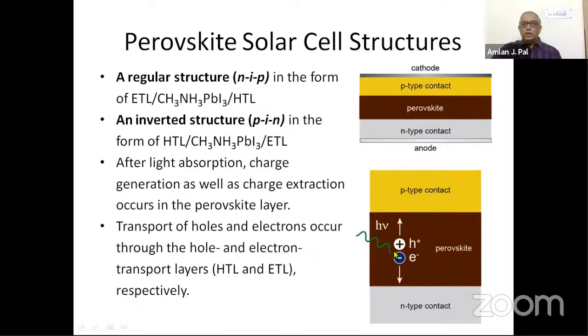So as soon as light falls, you have some kind of electron-hole formation in the perovskite. And because of the band diagram, as I said, we have chosen the P-type material and the N-type material in such a way that they form some kind of type 2 band alignment at both the interfaces, and because of this type 2 band alignment, charge separation will occur, and the holes will move towards one electrode and electrons will move to the other electrode and give you current in the external circuit when you just contact with the wire.